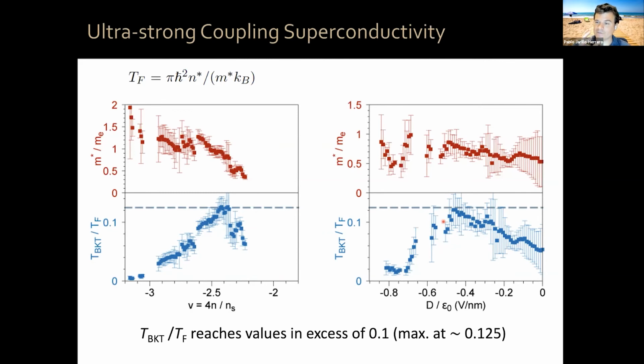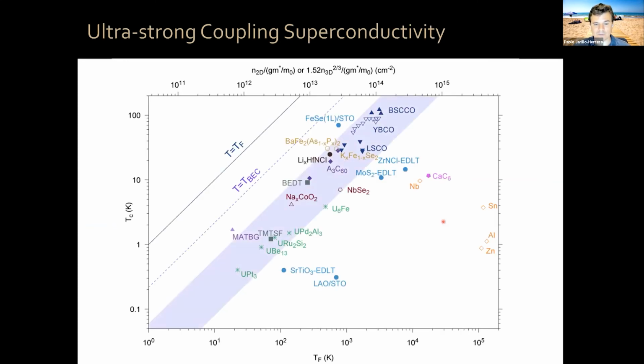So magic angle twisted trilayer graphene is the strongest coupled superconductor that exists. I'm going a little bit fast because I'm running out of time, but in this plot you can put a variety of superconductors in terms of critical temperature versus Fermi temperature. This tells you how strongly coupled a superconductor is. Unconventional superconductors are typically very strongly coupled, in this region. Conventional superconductors are weakly coupled, in this region. Magic angle twisted trilayer graphene is actually in this region. It's the strongest coupled superconductor that exists in the world. If couplings had the strength of magic angle twisted trilayer graphene, they would be well above room temperature superconductors. Another system has been recently realized that also reaches this ultra strong coupling.